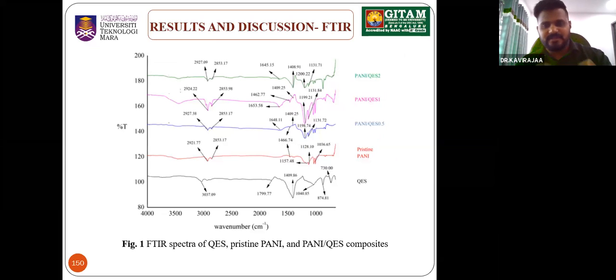Okay, so results and discussion for the FTIR. We all know that this is a very good fingerprint technique to identify the important functional groups, whether present in the composite material or not. Overall, all the functional groups that belong to the pristine PANI, which means the pure PANI, and also the eggshells are all present in the composite material, with a slight increase in wave number. This is one of the proofs that there is some kind of chemical interaction between these two materials, polyaniline and the eggshells. Next slide.